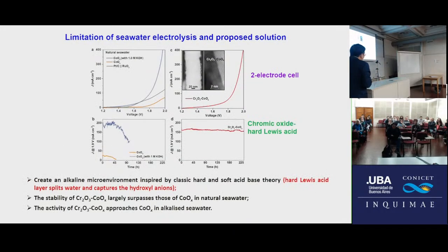Okay, so here, you can see from this figure slide, normally we can use cobalt oxide as a catalyst for water splitting, but you can see the activity is not so high. We must add a lot of alkaline solution to increase activity. For both of these cases, you can see stability is not so good, right? So you only run several hours. Okay, for our case, we combine two metal oxides together, and this is our performance. Keep in mind, we never add any alkaline solution, but this performance is very similar to this one, right? The reason is, as we just mentioned, on the catalyst surface there is a lot of OH minus, which makes the local environment alkaline.